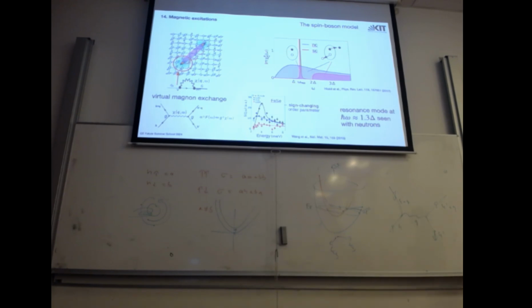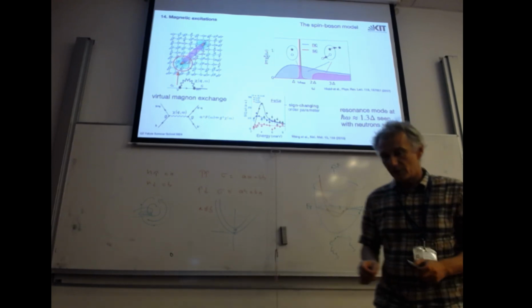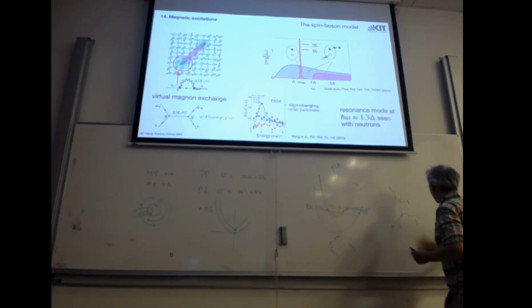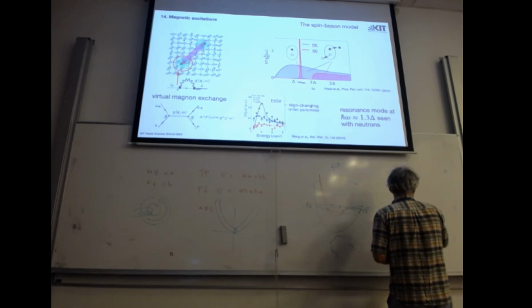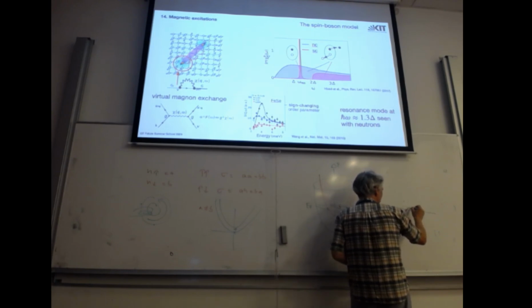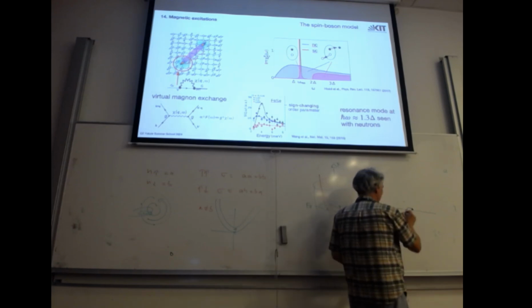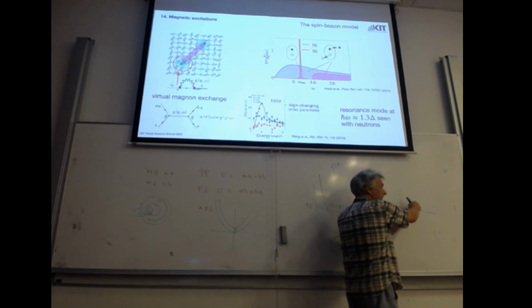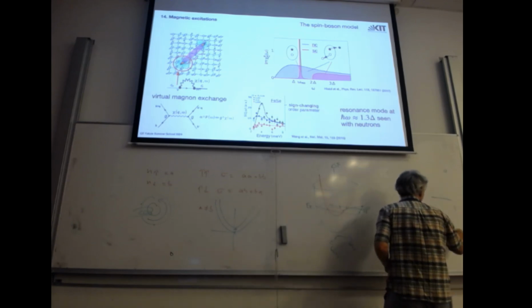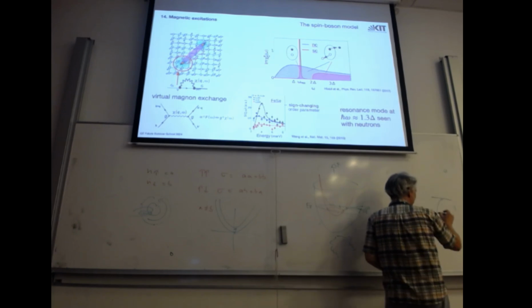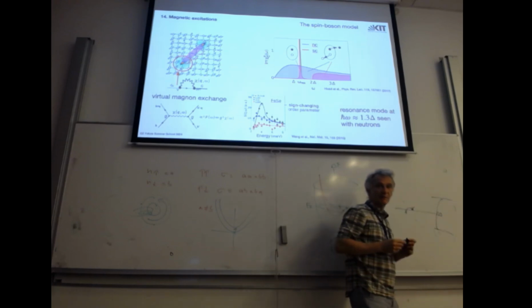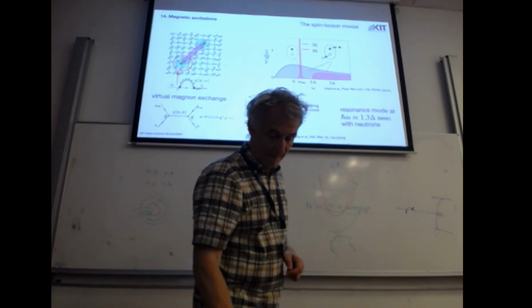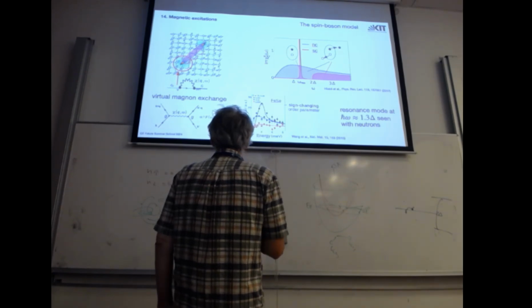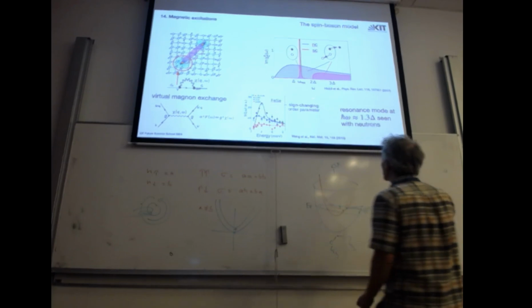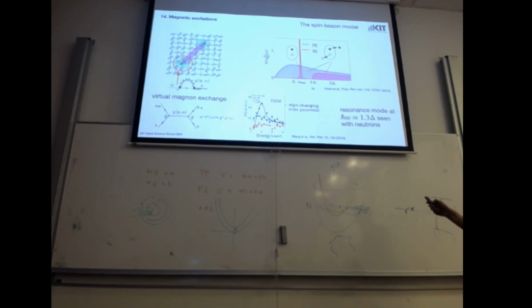Now we switch on superconductivity. So before, if we are not superconducting, I can spin flip an electron, creating a hole and an electron, at almost arbitrarily small energy. Now I want a superconductor again. So if I want to excite, I have 2 delta for spin flips to excited states. That means my magnon spectrum, if you like, or my susceptibility function, will start at 2 delta. So we're going from the normal state, all the spectral weight will be shifted away and can only start at 2 delta.